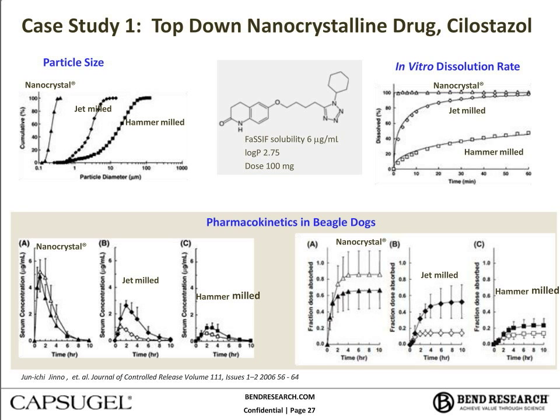However, it appears in this case the significant increase in bioavailability for the nanocrystalline suspension might be due to another factor besides dissolution rate enhancement, as the MAD calculation suggests a maximum absorbable dose of maybe only 10 to 20% of the 100 mg that was administered to the dogs here. So there may have been something else going on here, maybe a form change or solubilization from surfactants or something that might have increased the transient solubility of the drug compound in that particular nanomilled formulation.